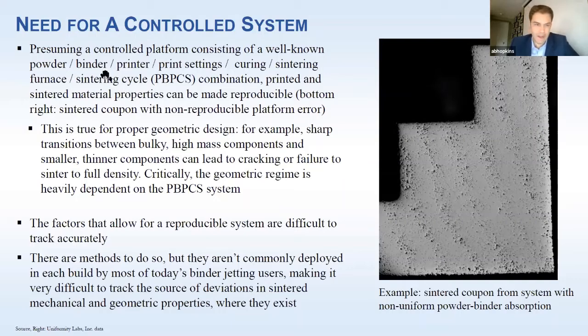So when you're layering the powder, are you laying down binder in a way such that it's evenly absorbed? And the printer itself has many different print heads, tens of thousands. They jet picoliter size drops or nanoliter size drops at a very rapid pace. Are they jetting them properly, repeatedly? Are the nozzles getting clogged? It's a hard problem. But you can get repeatable systems is what I'm getting to.